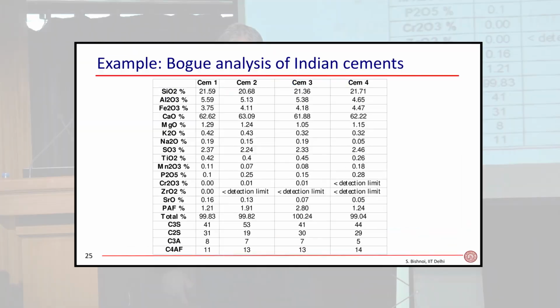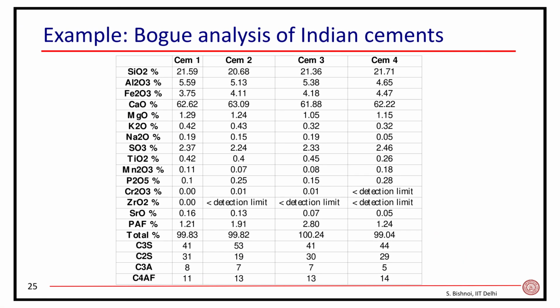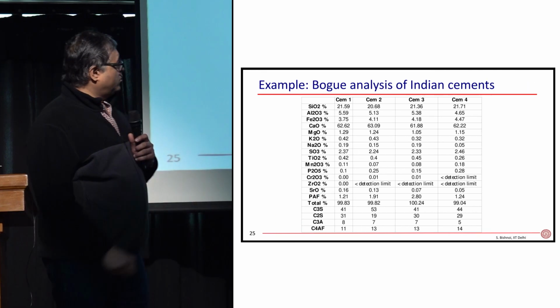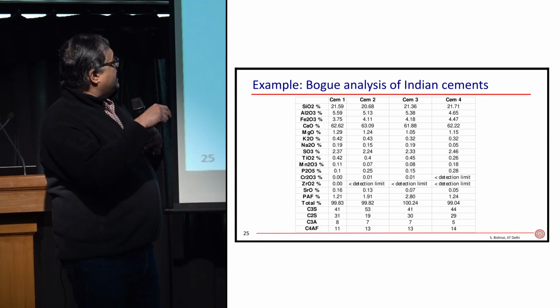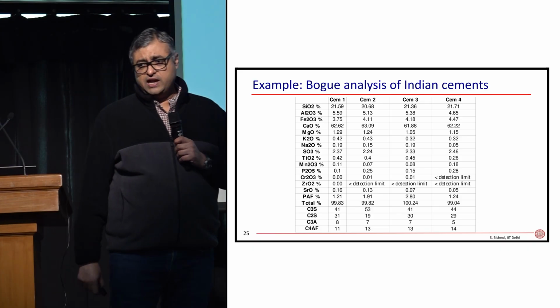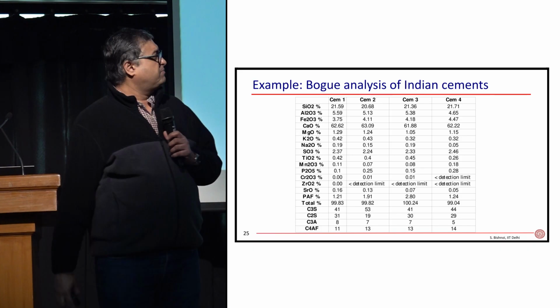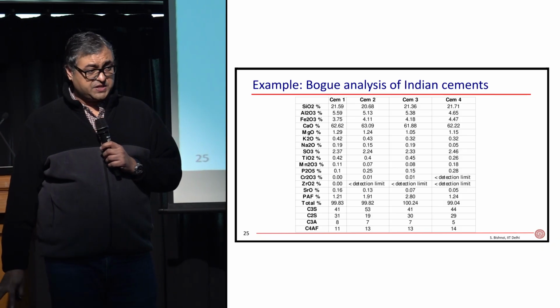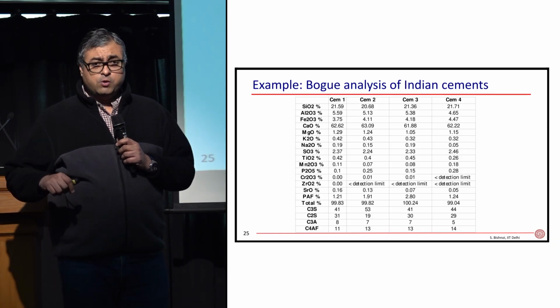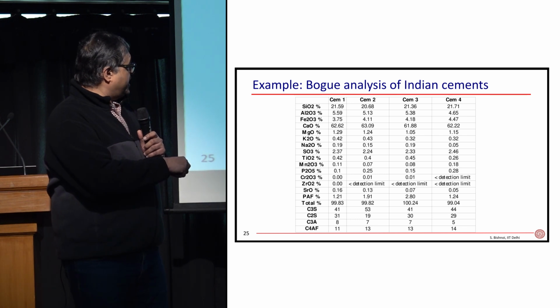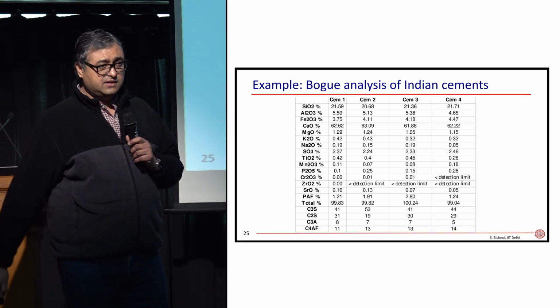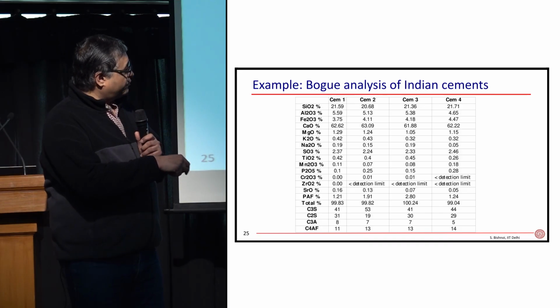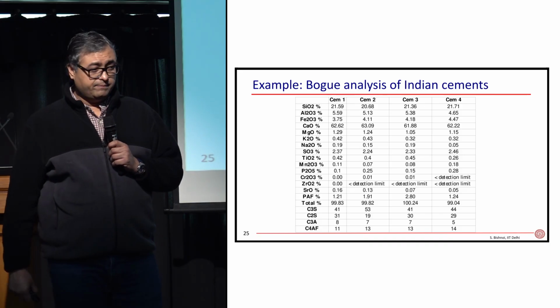Now, how good are those numbers? Let's try to understand that. Here I have data dumped compositions of 4 cements produced in India. If you look at these 4 cements, the individual compositions in terms of SiO2, Al2O3 and so on are not different by more than 1% or even 0.5%. And yet, if you use Bogue's formula to calculate how much alite, belite, aluminate, ferrite is present, you see a difference of 12% between them.